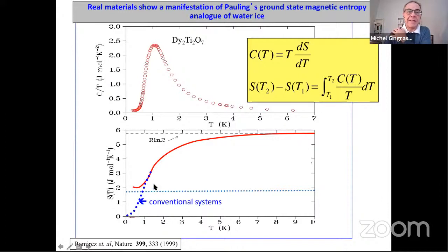But in spin ice, that's not what happens. The entropy saturates at the Pauling value within 10%. And this kind of result has been repeated over the last 20 years over a number of materials. If you remember, I don't have to have titanium on the B site. I can have tin, germanium, zirconium, and in all these varieties, by keeping the A site either holmium or dysprosium, the low temperature entropy is within 5 to 10% of the Pauling value. So this is the thermodynamic evidence that these systems are spin ices.